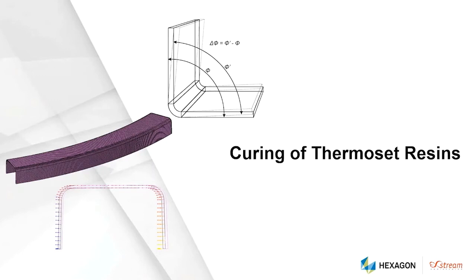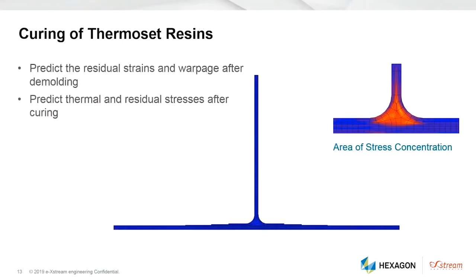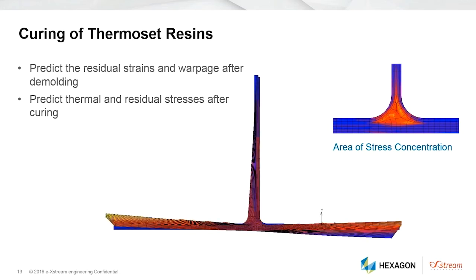Curing usually describes the hardening of a resin using elevated temperatures to obtain the final material properties. The problem of this process is that often parts deform and end up with residual stresses that can make the part unusable. Especially internal stresses in corners or roots can influence the structural performance and create delamination of layers within the material. Digimat helps to predict such critical areas in order to avoid creating weak spots in the manufactured part.